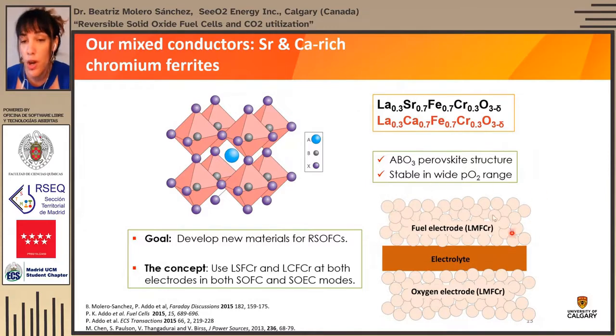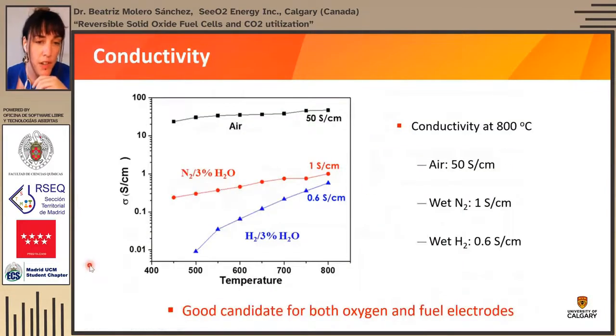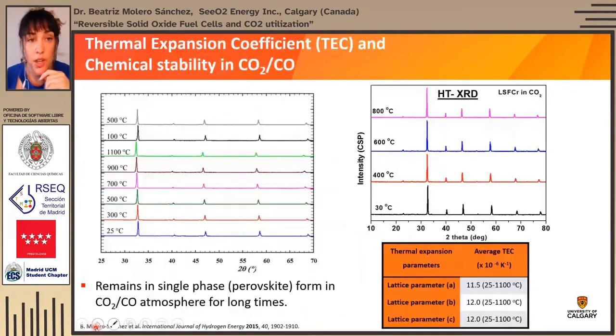Traditionally, you would use one composition for the fuel electrode and one composition for the oxygen electrode. So here we wanted to use the same material in a symmetrical configuration, so they really need to be stable in a wide range of PO2s. One of the first things that we need to find out is the conductivity, because they need to be good candidates to conduct in all of the atmospheres as fuel and oxygen electrode.